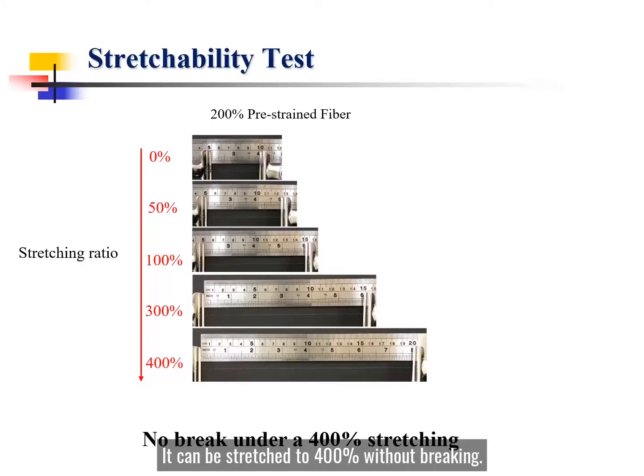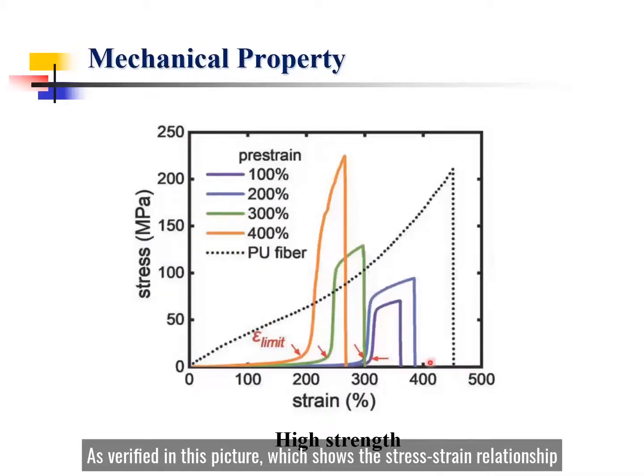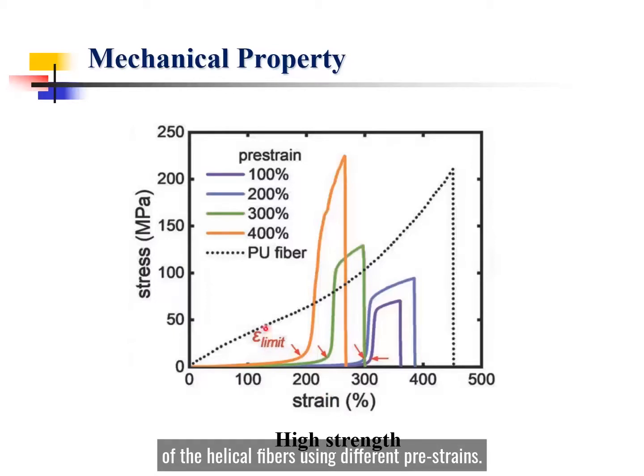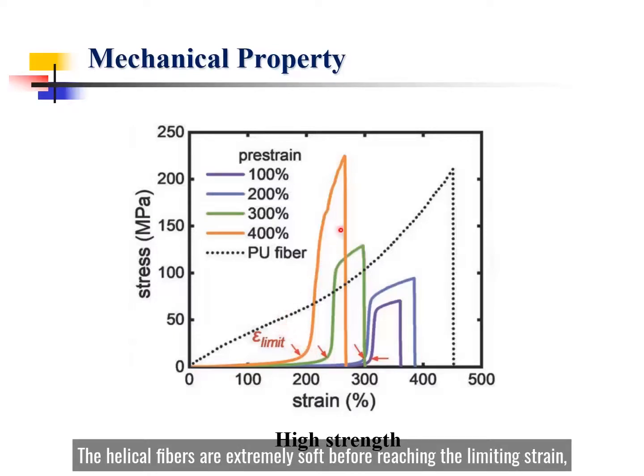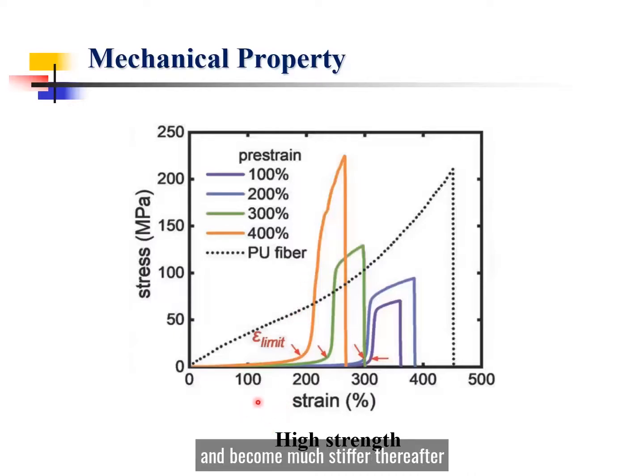It can be stretched to 400% without breaking. As verified in these pictures, which shows the stress-strain relationship of the helical fibers using different pre-strains. Since the helical angle increases with increasing pre-strain, the limiting strain decreases as the pre-strain increases. The helical fibers are extremely soft before reaching the limiting strain and become much stiffer thereafter because of the direct stress of the copper fibers.